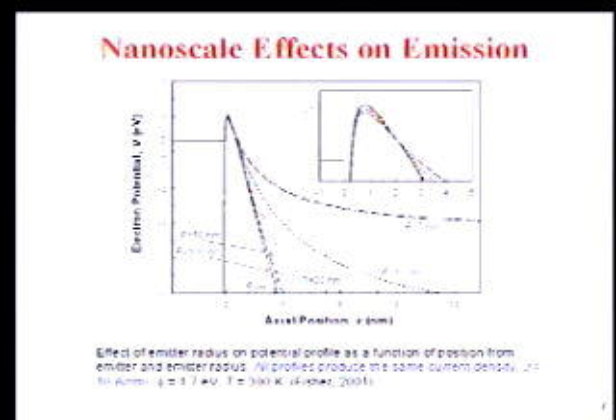Well, why is this important? If we take a variety of different materials and ask them all to produce 10 amps per square centimeter, which is what this graph represents, we can look at what the potential field looks like to produce that kind of current density. And so we have R equals infinity here. That's sort of the baseline. That's a planar emitter. And we get to 100 nanometers, and the profile hardly changes at all. 50 nanometers, not much. Then 20, it starts to change. And when we get down to about 5 nanometers, that potential profile has changed dramatically. Remember, all of these produce the same current density. Well, we can probably surmise just from that graph that even though the current densities are the same, the energetic distribution of the electrons that come out are probably significantly different.